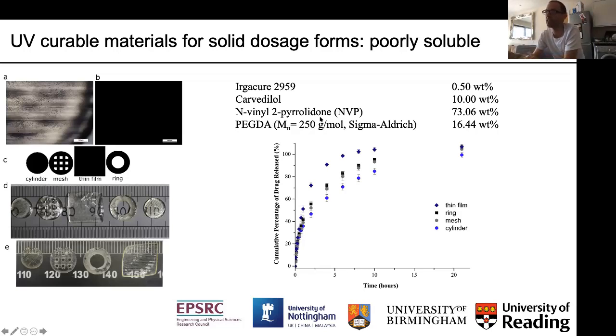And so as long as you can get the NVP out, or you can fully convert it, you have a nice form of a tablet in here. And as you can see from the release studies, that's the cumulative release, percentage of the release against the time. We can see we can get a reasonable release of that drug from that formulation. And we're able to print it in various different forms.